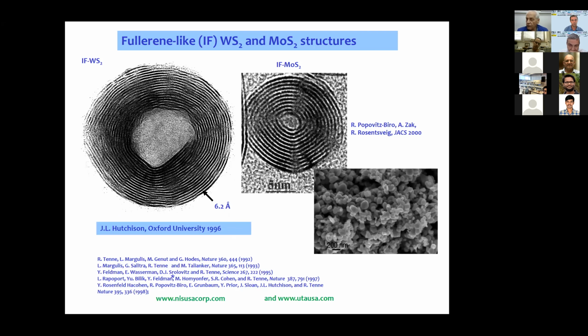And here you see the first generic nanostructure there, nanoballs, or spherical fullerene-like nanoparticles. Unlike C60, they are not made of a single layer, they are made of many layers, 10, 15 layers, and they are relatively large, 20, 30, 40 nanometers, containing millions of atoms. But nevertheless, they are all closed cage structures. And this is important for many of their properties.